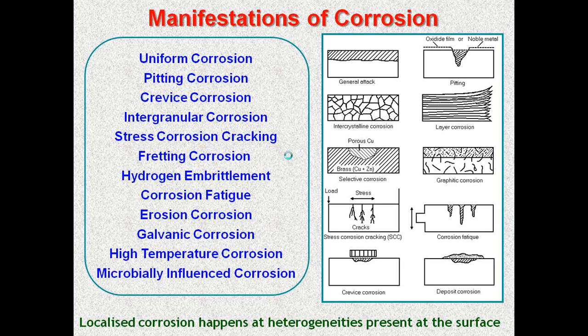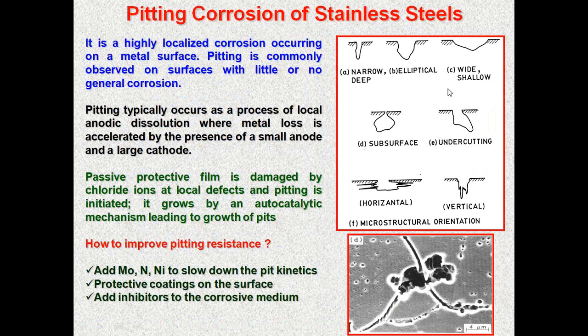I want to give a few important corrosion types of stainless steels. The most important is pitting corrosion, the formation of a cavity or hole on the surface, which can be narrow and deep, elliptical, wide and shallow, or a subsurface attack. On the top surface, you will never have a feeling of corrosion attack, but it may be very bulky at the bottom. And the undercutting, horizontal and vertical. Most of these pits are micrometer in size and below, so you will never know that it grows at the bottom of the metal surface into a very huge cavity, but on the top you will see only a micrometer attack.